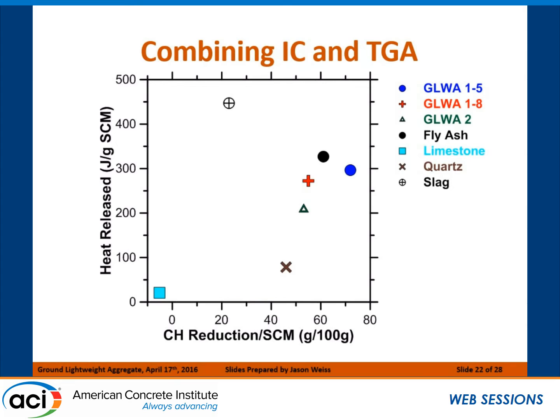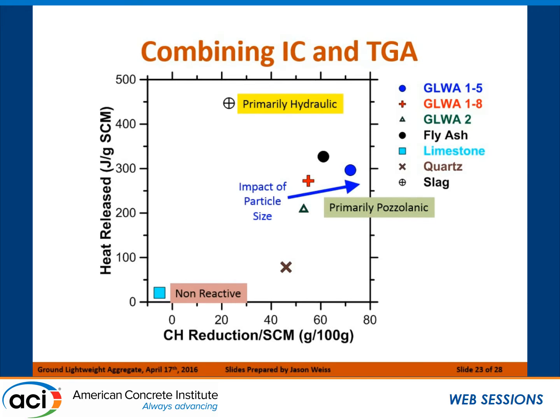So if we look at the heat that's coming out of each of these tests, we start to see a plot that looks something like this, where we see limestone down here, we see slag up here, all right? We've got our quartz, and then we've got our fly ash, which is this one, and then our 3 lightweight aggregates here. So the very interesting thing is when you start looking at this plot, all of a sudden now you can start looking at these and saying, we can start to classify these different powders based on where they fall on this diagram.